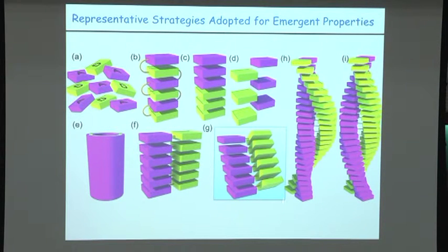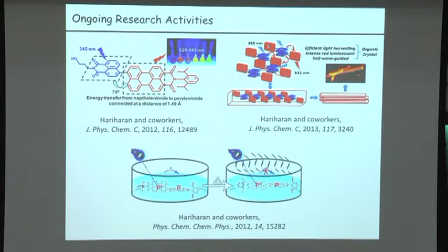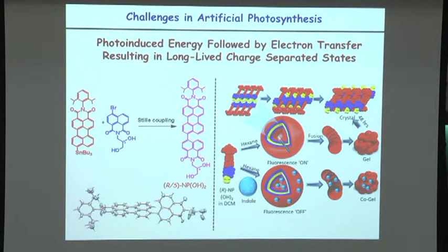will give a structure that has non-planar stacks. And these are the initial efforts that we worked on, wherein you have the donor and the acceptors near orthogonal to each other because of the steric hydrogen-hydrogen repulsion between two naphthalene units. We could succeed in getting some interesting features, but not the stacks that we were anticipating. And here you can see that just by modifying this particular group, the side chain, we can attain a vesicular architecture that will have stacks of this perylenimide chromophore, wherein you can have the electron or the hole transported across the stack.